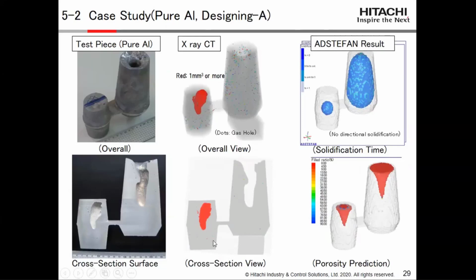An X-ray CT also shows the phenomenon, and this shows the result by ADSTEFAN. In ADSTEFAN, the red area shows the possibility of casting defect in porosity prediction. So in this case, the riser size is very narrow and relatively long. So in this gate design, the design is not so good.